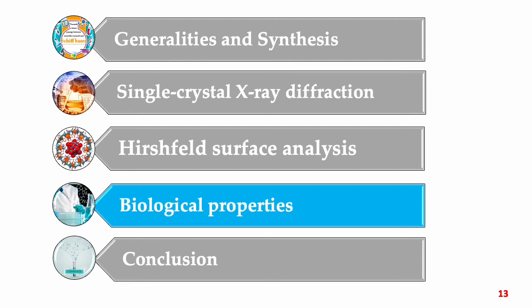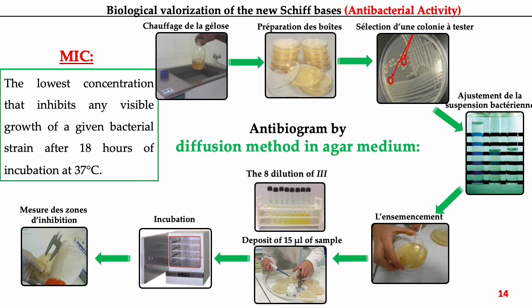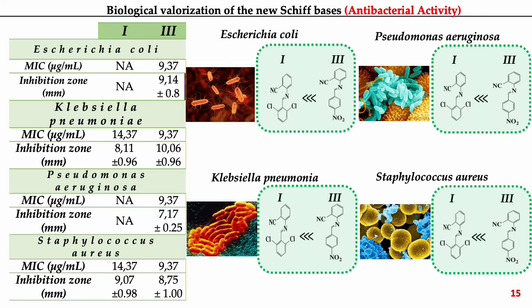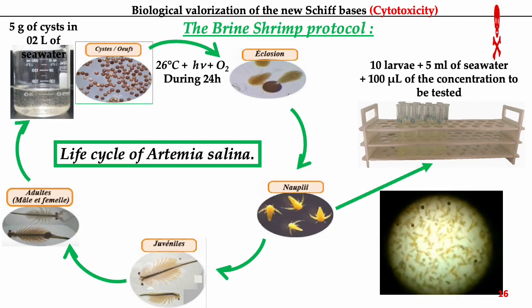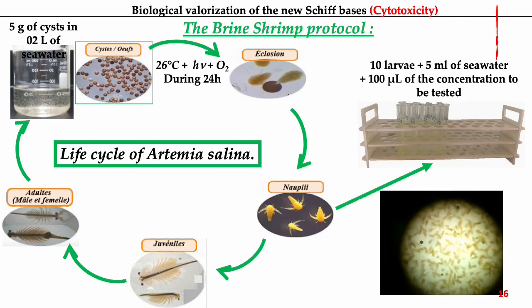The fourth part of our work is the study of the biological properties of the new Schiff bases. The antibacterial activity of our compounds was carried out using the antibiogram by diffusion method, which allows us to determine the lowest concentration that inhibits any visible growth of a given bacterial strain after 18 hours of incubation at 37 degrees. We tested our compounds on 4 bacterial strains. The comparison of the MIC of each bacterial strain and for each compound indicates that the Schiff base derived from 4-nitrobenzaldehyde has the more significant antibacterial activity compared to that derived from 2,6-dichlorobenzaldehyde.